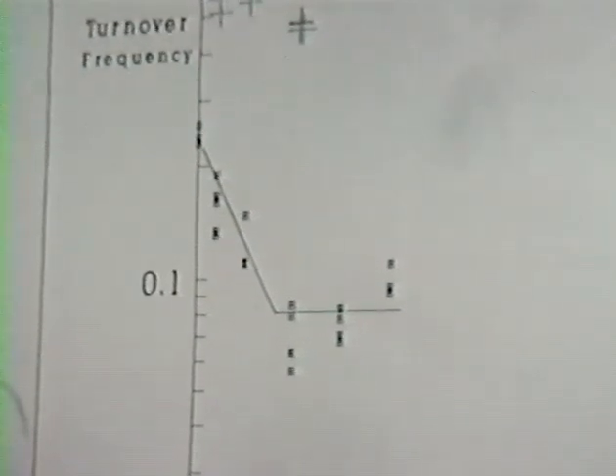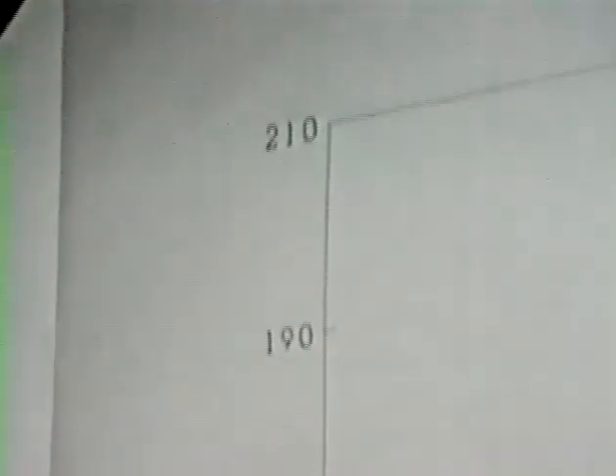At slightly higher temperature, we don't see the initial fall-off in activity. Extrapolating data for pure ruthenium using an activation energy, the edges and corners are now lower in activity than the basal planes. The reason is that the activation energy varies significantly as we add copper: pure ruthenium has an activation energy close to 130 kJ/mol, but as we fill up the low-coordination edge and corner sites, it jumps to close to 190 kJ/mol. Since the activation energy on the base planes is higher, at low temperatures edges and corners are more active, but at higher temperatures there's a crossover and the base planes show higher activity.